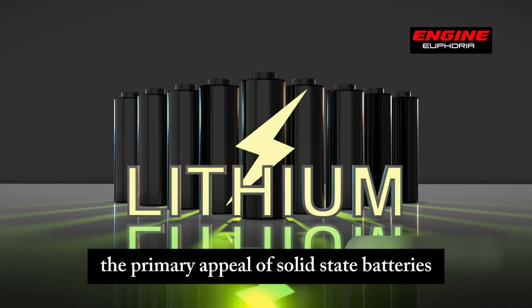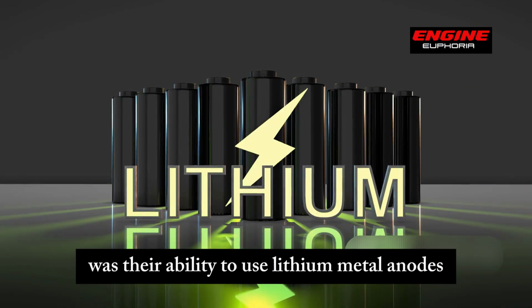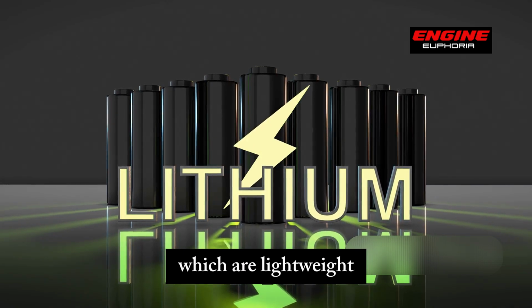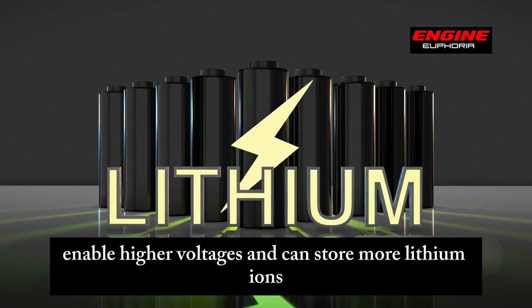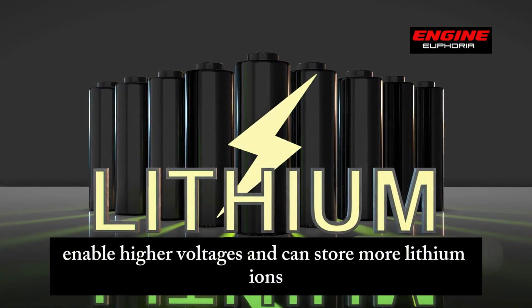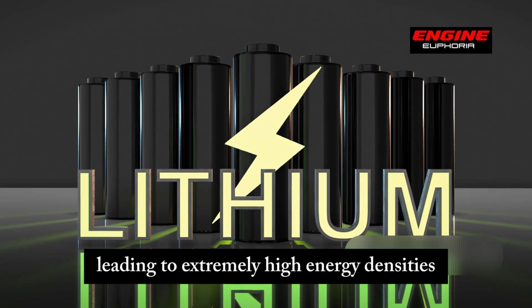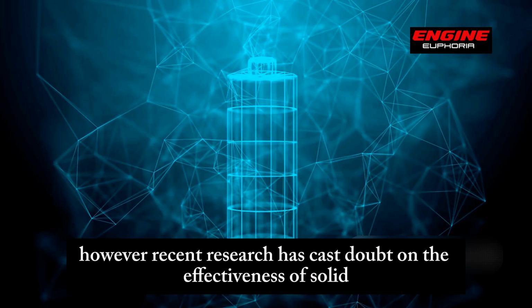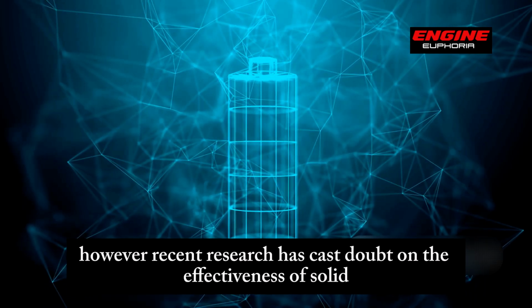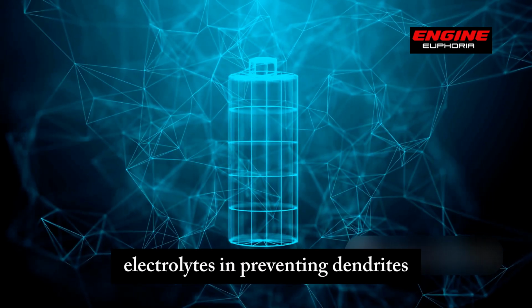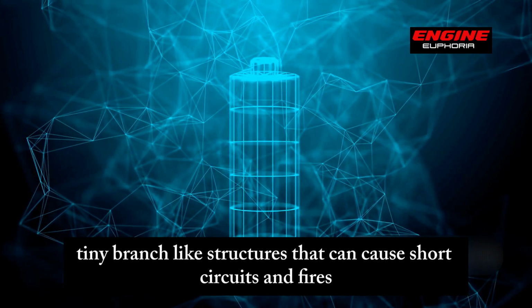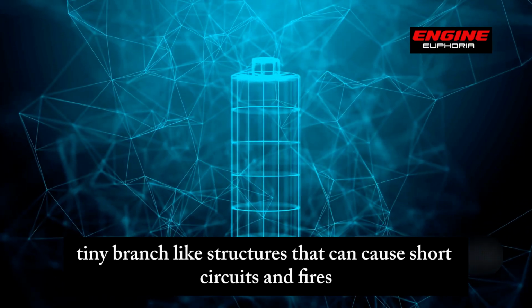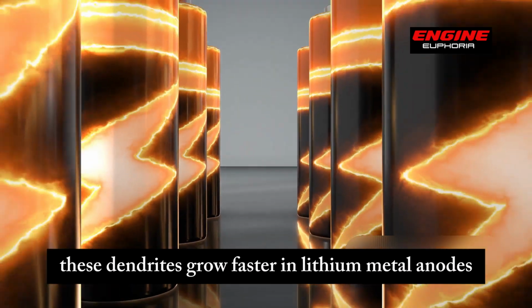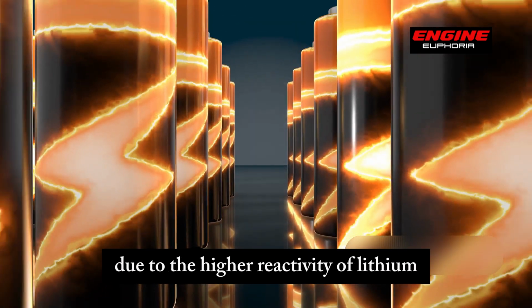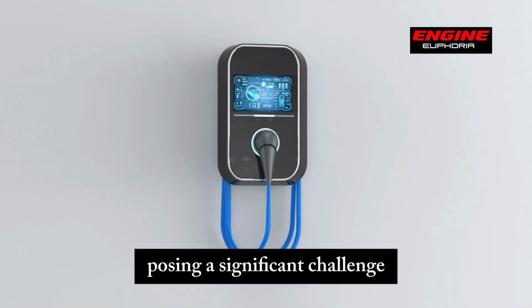The primary appeal of solid-state batteries was their ability to use lithium metal anodes, which are lightweight, enable higher voltages, and can store more lithium ions, leading to extremely high energy densities. However, recent research has cast doubt on the effectiveness of solid electrolytes in preventing dendrites, tiny branch-like structures that can cause short circuits and fires. These dendrites grow faster in lithium metal anodes due to the higher reactivity of lithium, posing a significant challenge.